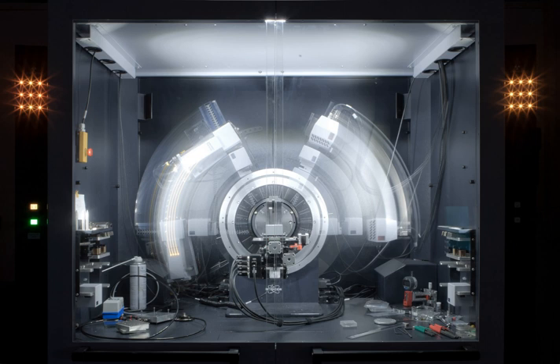To collect all the necessary information, the crystal must be rotated step by step through 180 degrees, with an image recorded at every step. Actually, slightly more than 180 degrees is required to cover reciprocal space, due to the curvature of the Ewald sphere. However, if the crystal has a higher symmetry, a smaller angular range such as 90 degrees or 45 degrees may be recorded. The rotation axis should be changed at least once, to avoid developing a blind spot in reciprocal space close to the rotation axis.